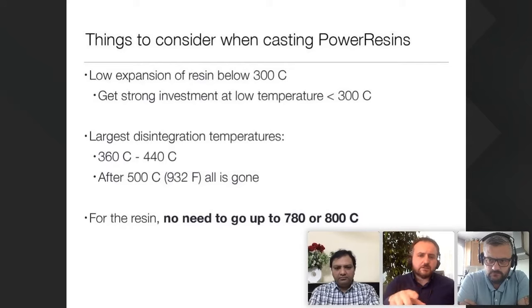Now, I just have these slides for our customers when they cast PowerResins, what they need to think about. So there is a low expansion of the resin. So we want an investment that is strong, but if we look at the resin side of it, we want it to be strong below, let's say, 300 degrees. It doesn't really matter if it's strong at 700 degrees because there is no more resin anymore in it. So you want it strong when the resin is burning out, right?